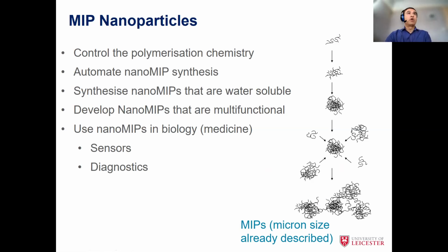Well, we want to control the polymerization chemistry. Normally when you polymerize something, it's an uncontrollable radical polymerization reaction, and you end up with a solid lump at the bottom. And essentially that's what I've shown you. You end up with a solid lump, you actually wash it and grind it, and you end up with particle sizes. So you start off with a monomer, you end up with a very hard polymer at the end.